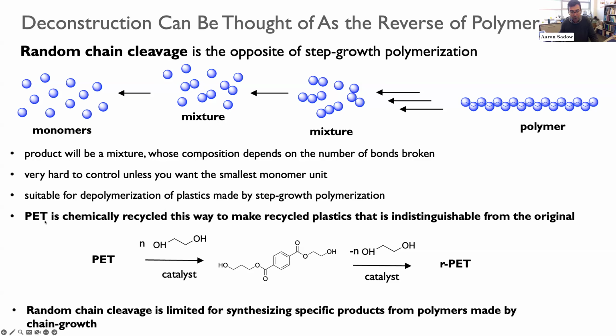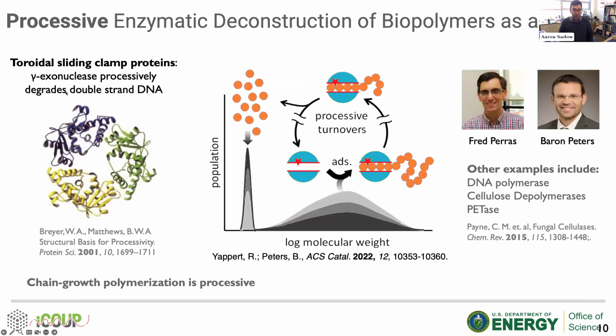That works really well for things like PET, where you have monomers of specific size and specific units, functionality that could be cleaved to build monomers that could be repolymerized. But from something like polyethylene, where the distinct monomer is ethylene, and that depolymerization is uphill by a large amount, you can't add a reagent to generate ethylene from polyethylene readily, then you have competing reactions, and it's very hard to get back in high yield to these monomers.